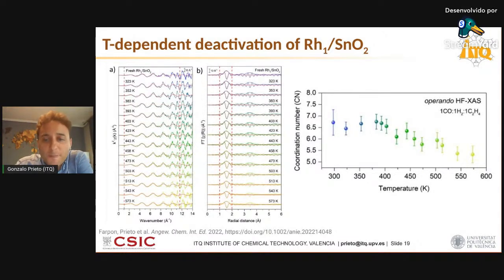These results show X-ray absorption spectroscopy again. So they show the XAFS spectra both in Fourier transform as well as in K space at different operation temperatures under operando conditions. So the catalyst is being exposed to the hydroformylation gas composition, which is equimolar in CO, hydrogen, and ethylene. And believe me, we did all our homework, we did our fits, and there is absolutely no sign of rhodium-rhodium direct coordination. So rhodium is not agglomerating into clusters under these reaction conditions. That is not the reason for the deactivation.